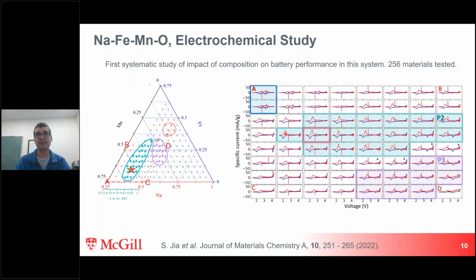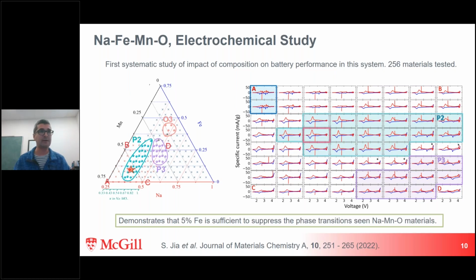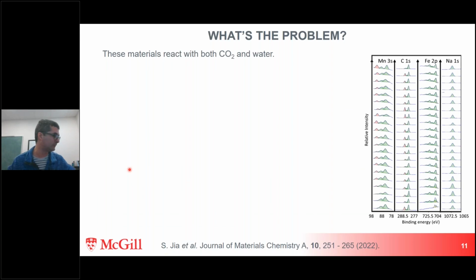If you add 5% iron and 10% iron, those little wiggles are gone. And in this P2 phase, systematically you get a very smooth curve. And so we know, and we did extended cycling, and we know that this leads to really good performance. And so in terms of energy density and cycling, the best material in this phase diagram was this one here. So this is the star, okay? So that's great. We found that 5% iron is sufficient to suppress the phase transition, 10%, you know, really good performance. So what's the problem? Why are we not, you know, filing patents and going to the commercialization? And the main reason is air stability.